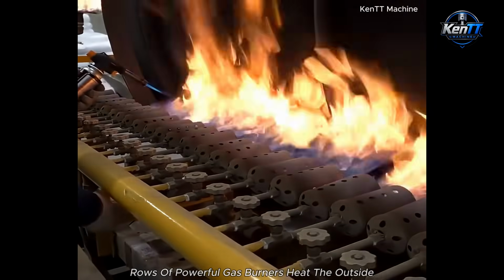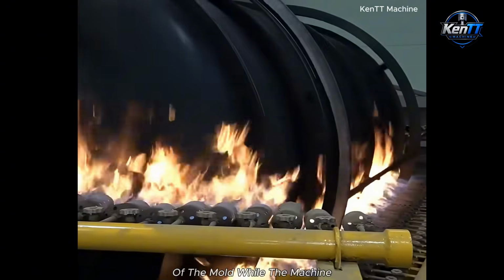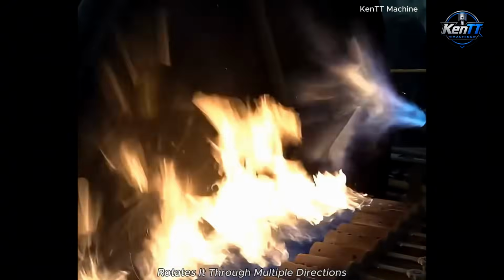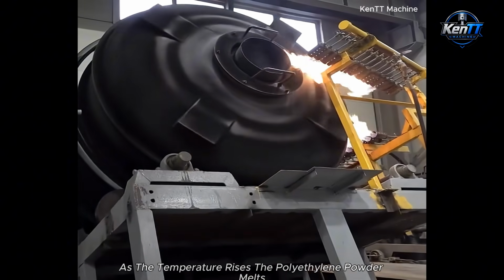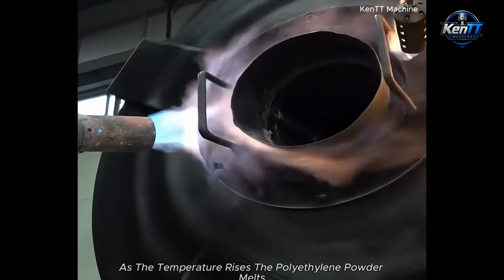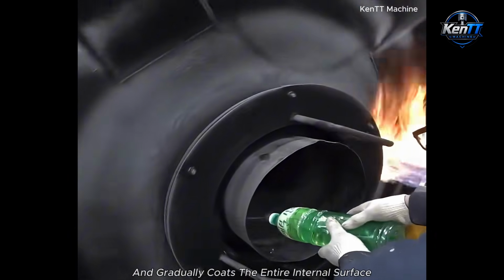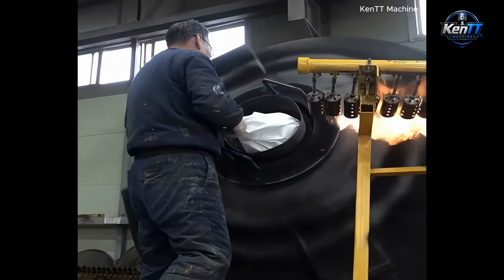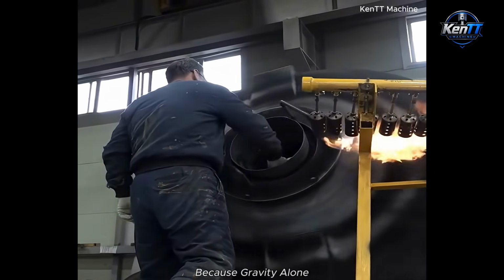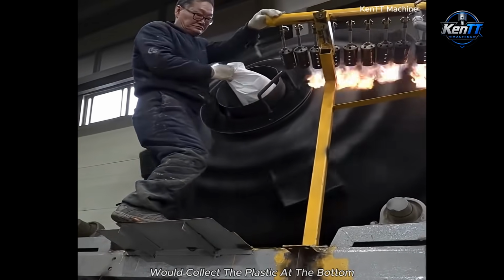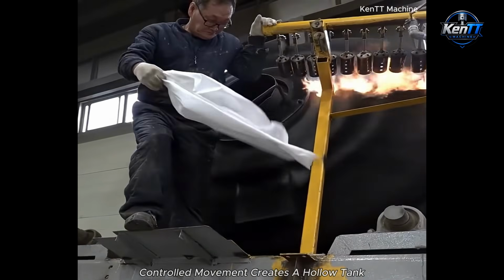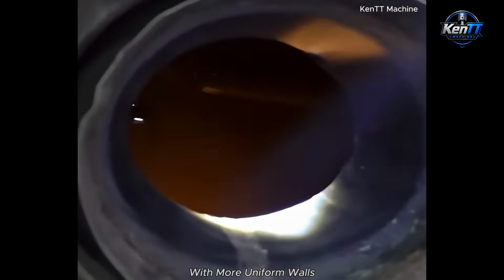Rows of powerful gas burners heat the outside of the mold while the machine rotates it through multiple directions. As the temperature rises, the polyethylene powder melts and gradually coats the entire internal surface. Continuous rotation is essential because gravity alone would collect the plastic at the bottom. Controlled movement creates a hollow tank with more uniform walls.